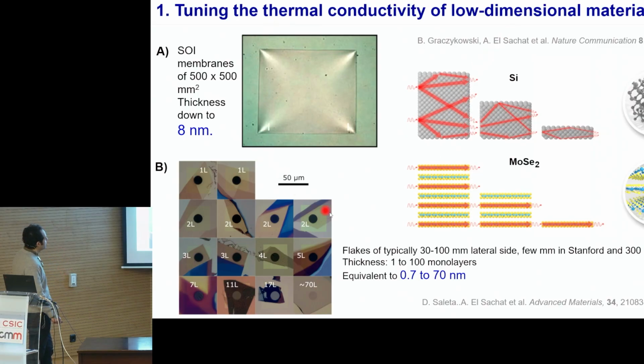So here, what we do is we started from bulk silicon, and we went down to 8 nanometer thick silicon membranes. And in the second study, we also did this with molybdenum diselenide. We exfoliate layers from 1 layer until 70 layers, and we measure the thermal properties of this material. There's the in-plane thermal conductivity, and the idea here is that by decreasing the thickness of the silicon membrane, actually you increase the phonon boundary scattering, so you can really decrease the thermal conductivity.